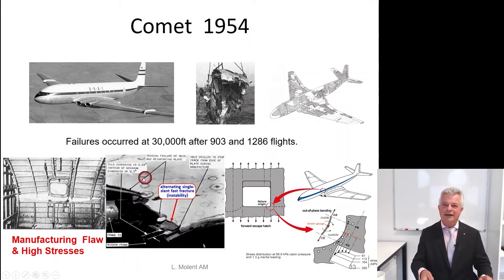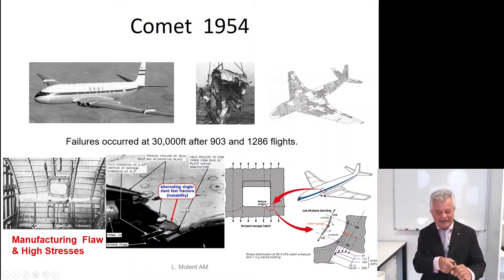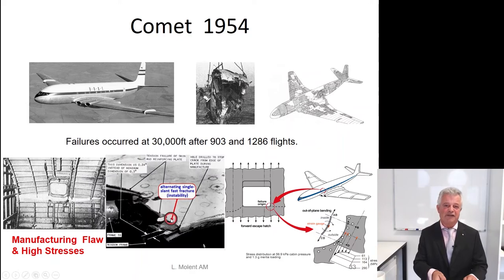Number two, it just so happened that during the manufacture, the riveting process used, what was it called, a punch riveting process, one of the punched drilled rivets tore or produced crack-like features exactly coherent or co-located with the high stresses, and that led to the fatigue failure of more or less two aircraft with the loss of 100 lives.